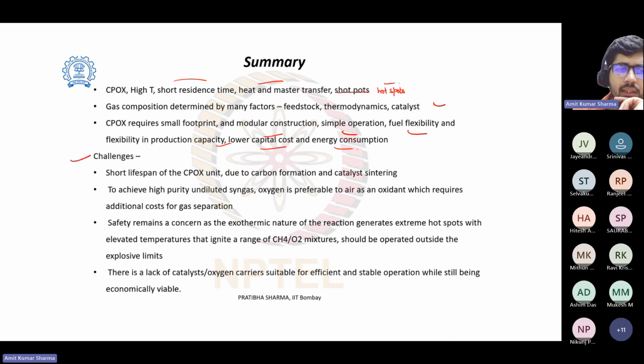The challenges are the short lifespan of the unit due to carbon formation and catalyst sintering. So there can be carbon formation and sintering, and that will damage the catalyst. To achieve high purity undiluted syngas, oxygen is preferable to air as an oxidant, which requires the additional cost of gas separation. High purity or undiluted means there will be no nitrogen, so you need a different unit for air separation. So it will increase the cost.